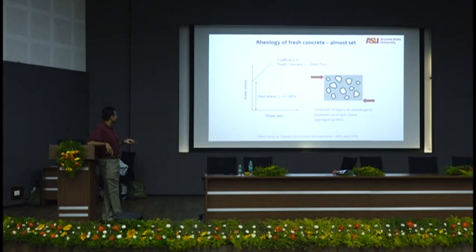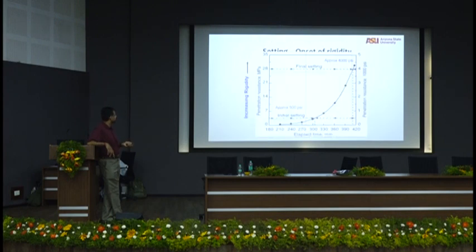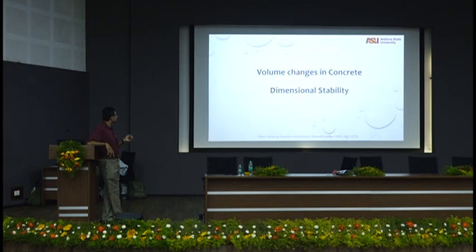So at about 5000 pascal second, that kind of viscosity, it's very difficult to move the system, and that's a very solid system. You can see here the picture also tells you that between the grains nothing has formed. You see a slightly thicker layer and then an even thicker layer, so much more structure formation. Onset of rigidity, skip all of that.